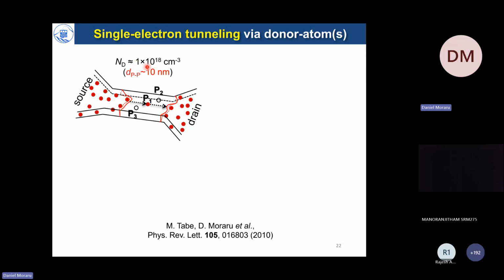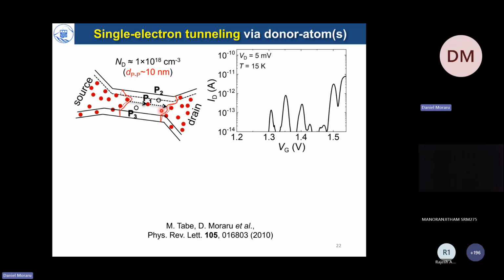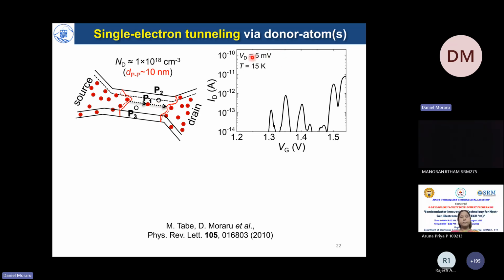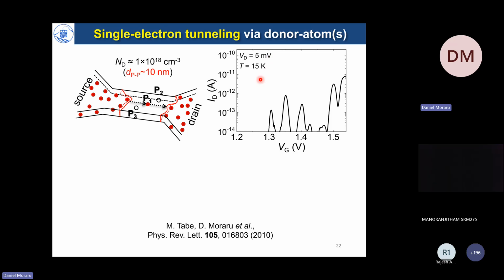So we started by doping our channels to a concentration of 10^18 per cubic centimeter, which means that the distance between two dopants is on average 10 nanometers. Now, considering that the Bohr radius is about 2.5 nanometers, this is sufficient distance that the dopants are not influencing each other too much. So we can treat each of them as a distinct individual dopant. So in such a channel, despite the random distribution of dopants, we may have the source and the drain bridged by several of these individual dopants, and we measure the IV characteristics at low bias and also at low temperatures.